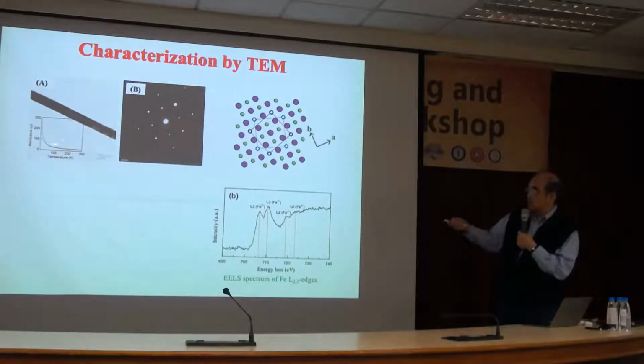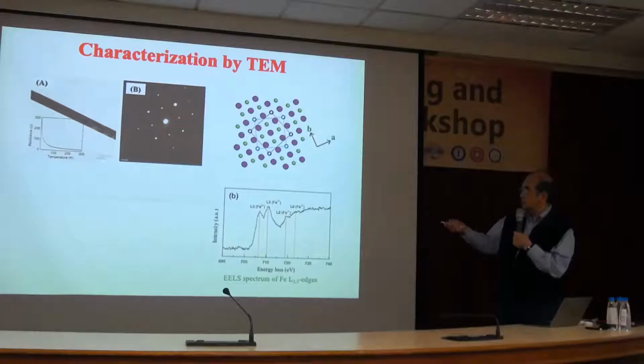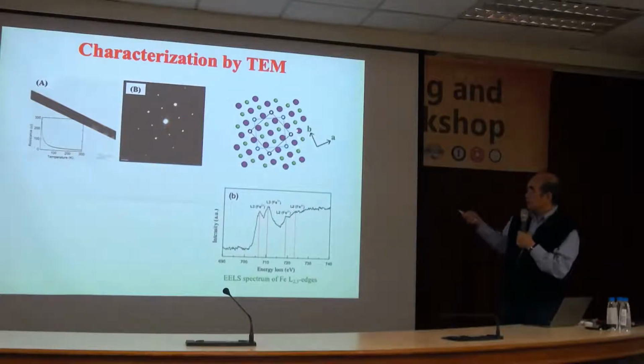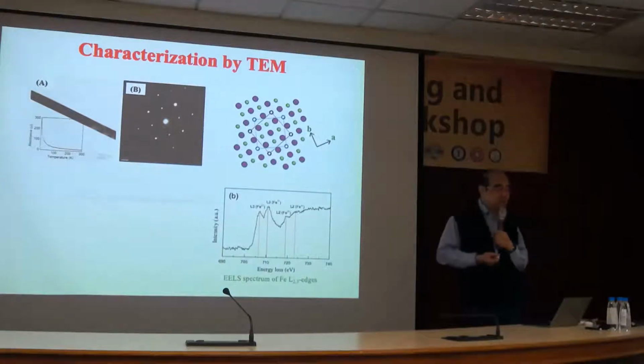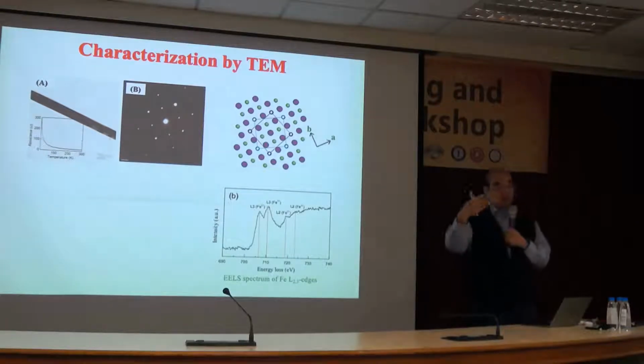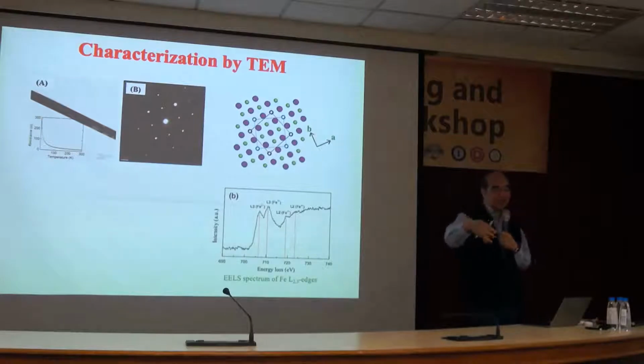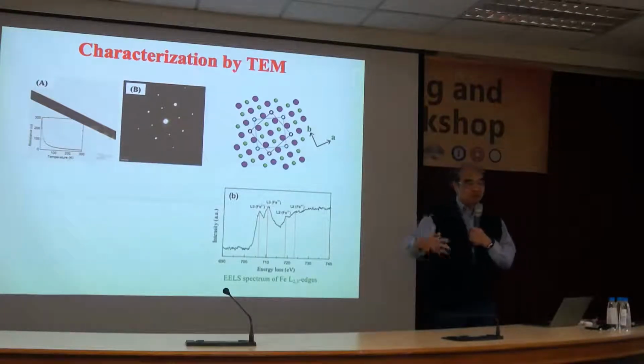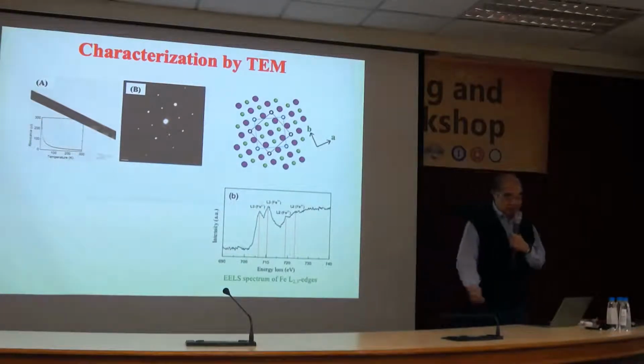There's a metal insulator transition around 30 Kelvin, and it can be well described with this model. And there are two iron valence states, 2+ and 3+, in this material. You have L2 and L3. So the iron cannot be purely 2+. You have a certain part in the 3+ state.